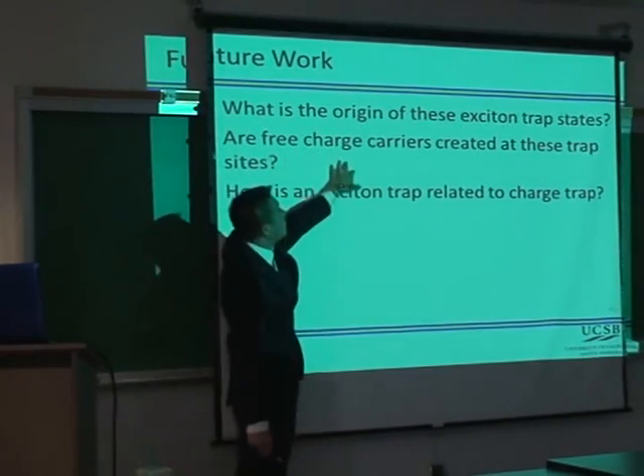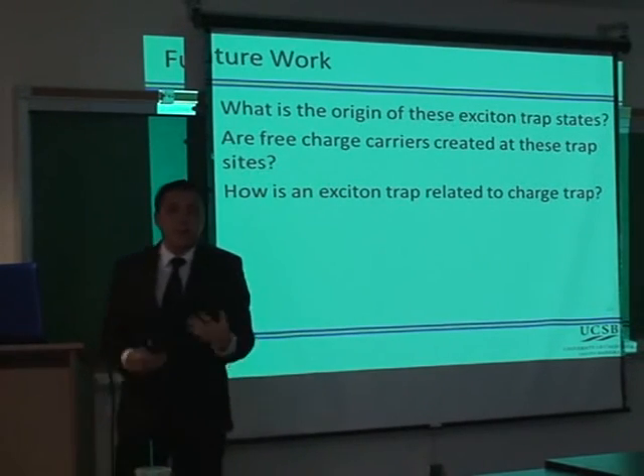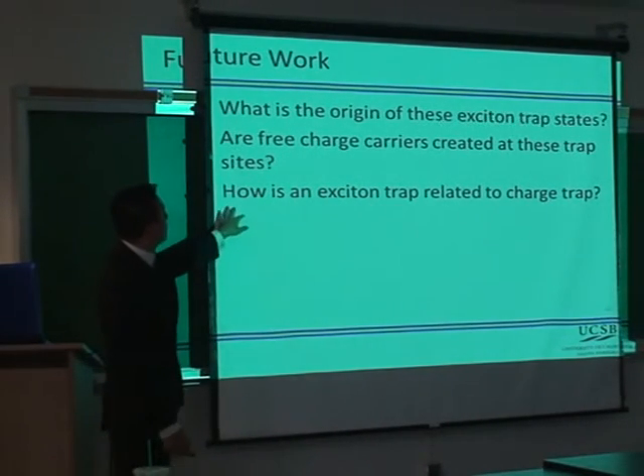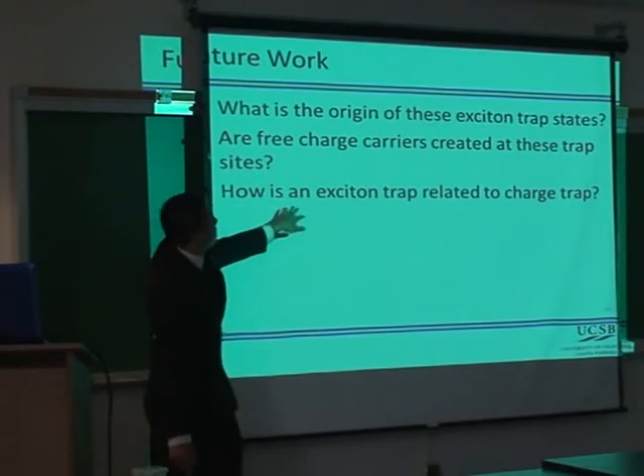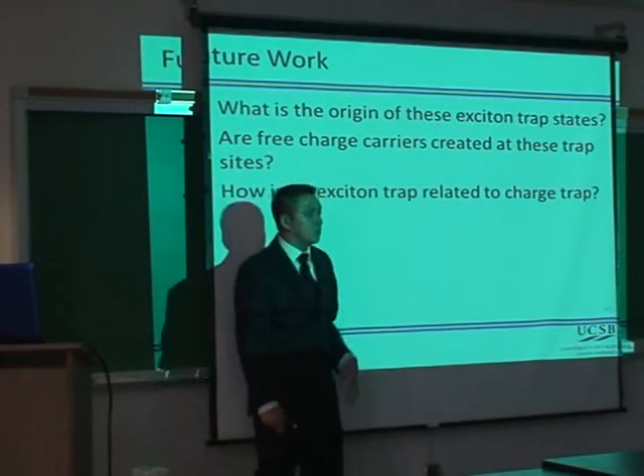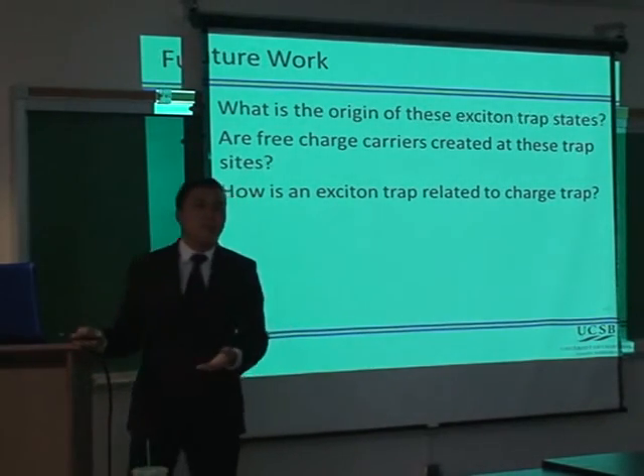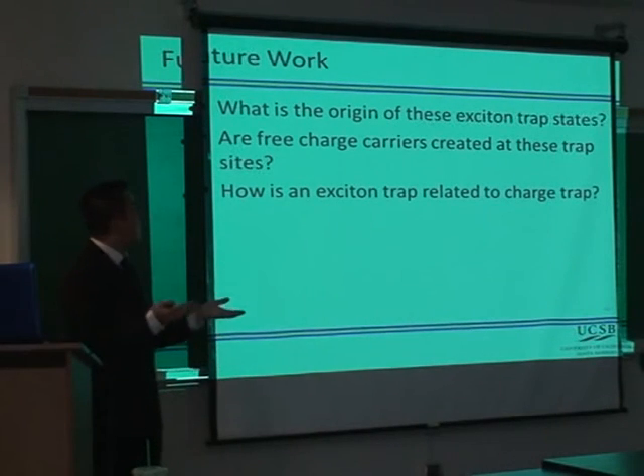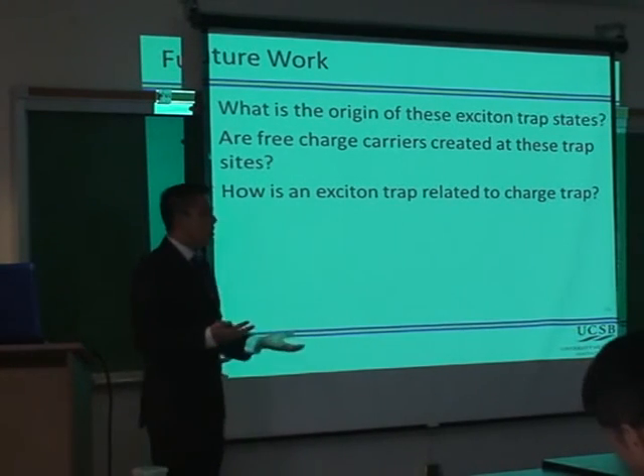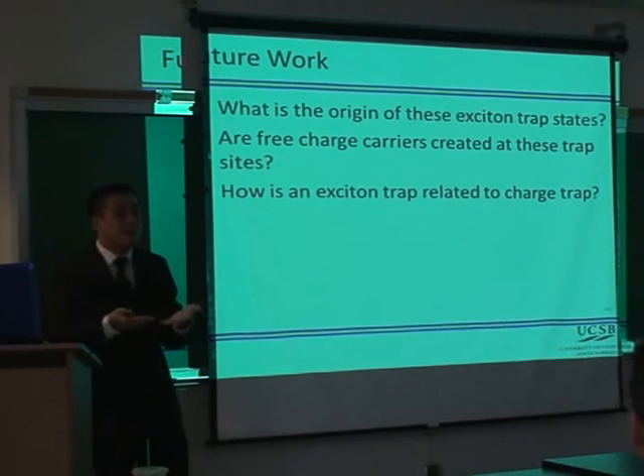Are free charge pairs generated there? Maybe that could be a useful thing. In addition, how is an exciton trap related to a charge trap? There's previous work that showed the density of charge traps is almost equivalent to the density of exciton traps. So the question is, are they the same thing, or are they kind of the same thing? How is that connection actually?